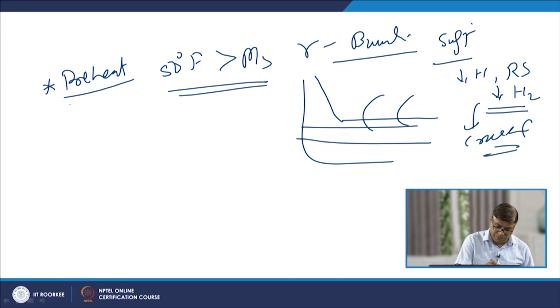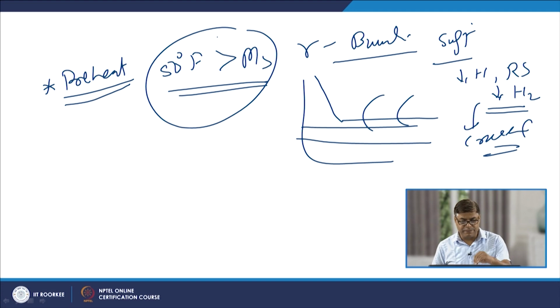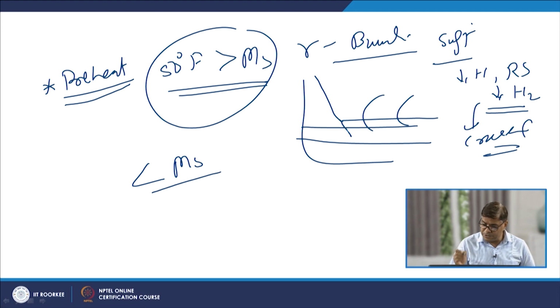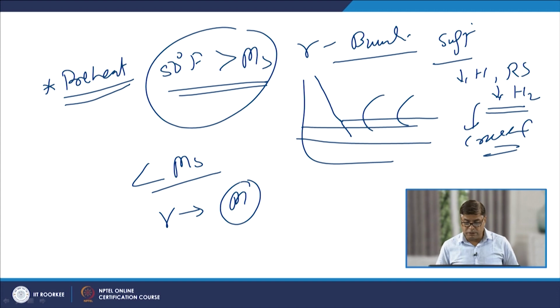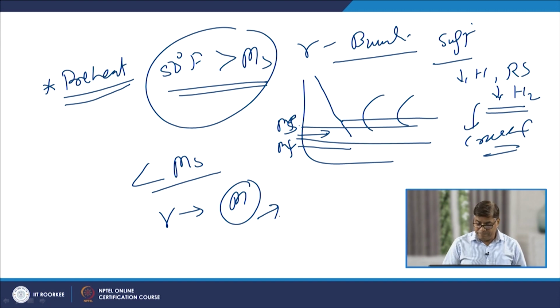So, this is one thing that if possible, then use the preheat temperature greater than 50° Fahrenheit above the MS temperature, that is the martensite start temperature. And if this is not possible, like the preheat temperature is less than MS temperature, then certainly some of the austenite will be transforming into the martensite. That will depend upon what is the value of preheat. Like if the preheat temperature is below MF temperature, then complete austenite to martensite transformation will be taking place, and if the preheat temperature is between the MS and MF temperatures, then there will be partial transformation of austenite to the martensite,